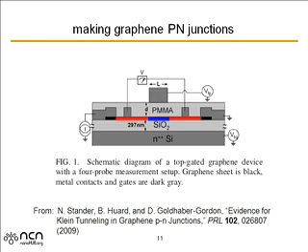Typical numbers are in the order of 50 nanometers. For this device, the oxide thickness is quite large, so the transition width is about 100 nanometers. Now there are some devices, and it'll turn out these negative index focusing devices need junctions that are much more abrupt than that. So one of the challenges to realize those devices is going to be to make junctions that are more abrupt. But the width of that transition region turns out to be really important to understand the IV characteristics. So we'll talk a lot about that.